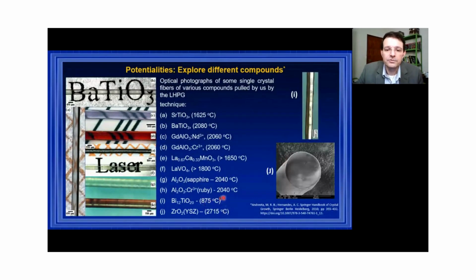So you can produce materials with a low melting point, which for us is about 800 degrees Celsius, up to zirconium oxides, at nearly 3000 degrees Celsius. So you can explore a huge amount of compounds in a single crystal form.